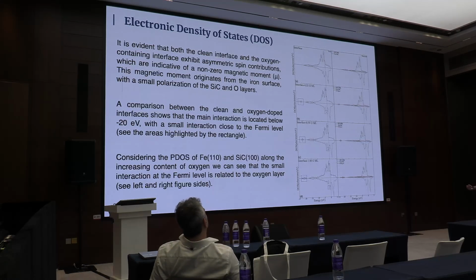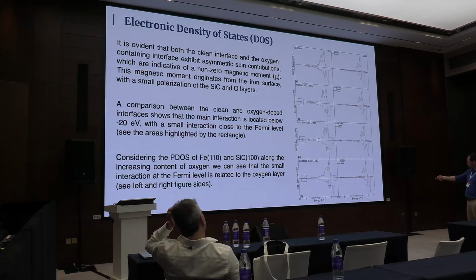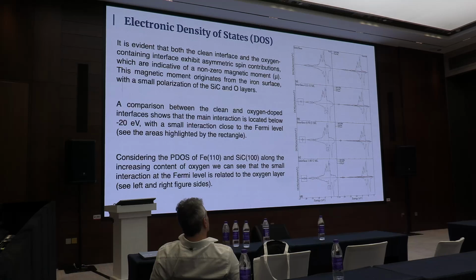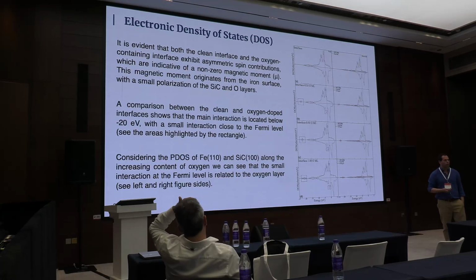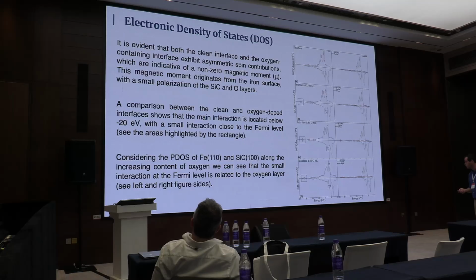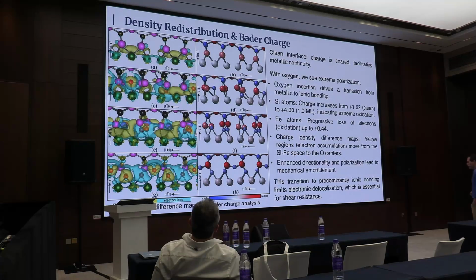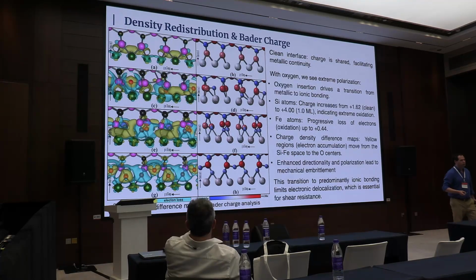So the curves move a little bit to lower energy, which is saying that the system is stabilized, so it likes having the oxygens. And we observe that the up and lower parts of the curves are not symmetric. It implies that the amounts of up and down electrons are different, so it implies that we have magnetism. And this magnetism is coming mostly from the iron. Okay? This is normal. This is something that is expected. So we are on the right pathway. Okay, this is the part we have, and we will start now to understand.